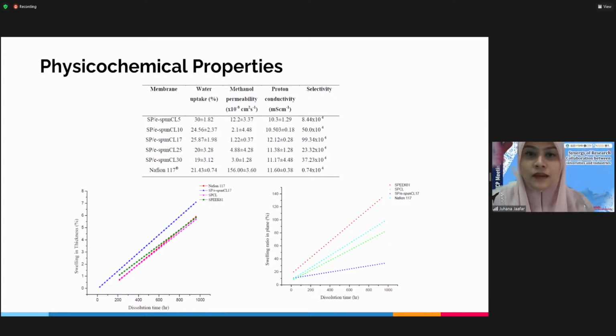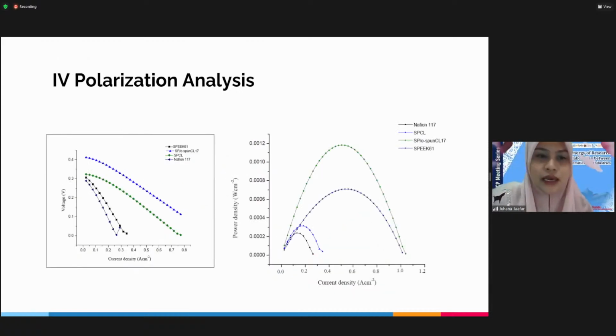Okay, and this is the IV polarization analysis, expressed in the form of power density. It also shows a result synchronized with the physicochemical properties results. As I showed here, the SPEEK/e-spun CL17, meaning that the SPEEK consists of the electrospun chloride at 17 weight percent, exhibited the highest power density as compared to other membranes.